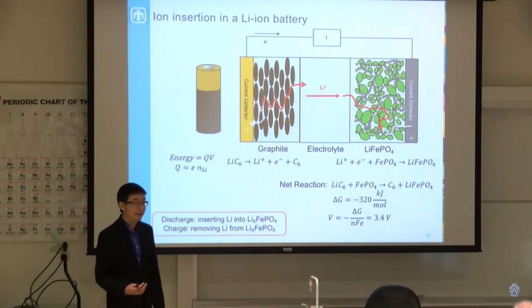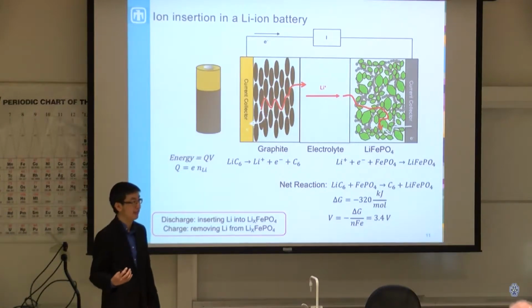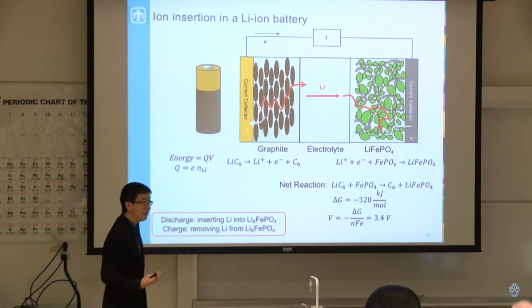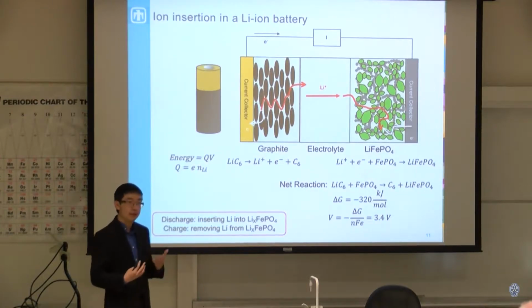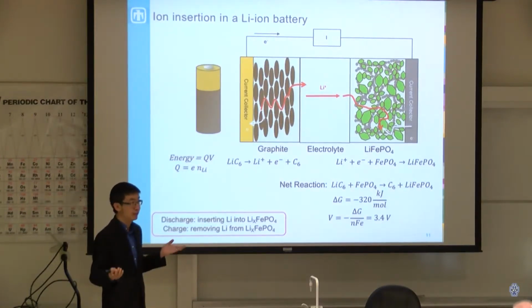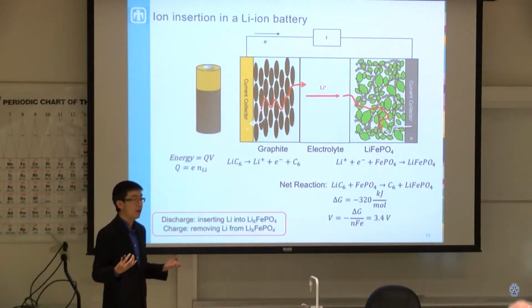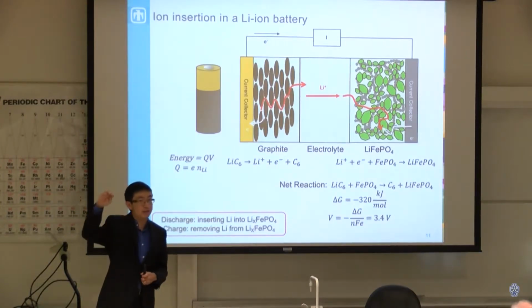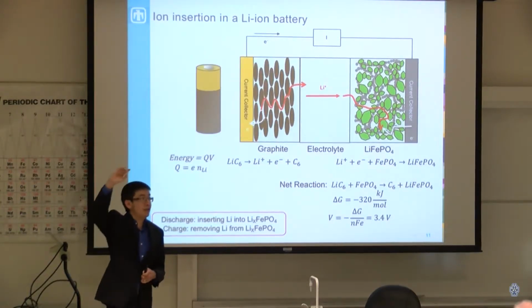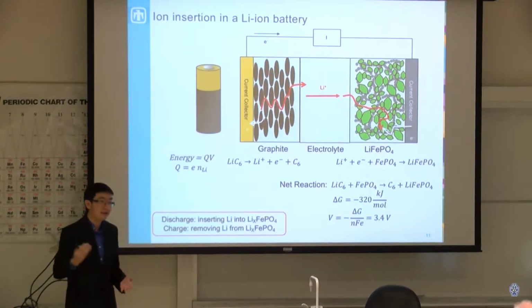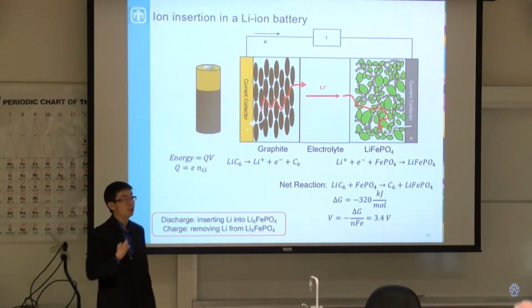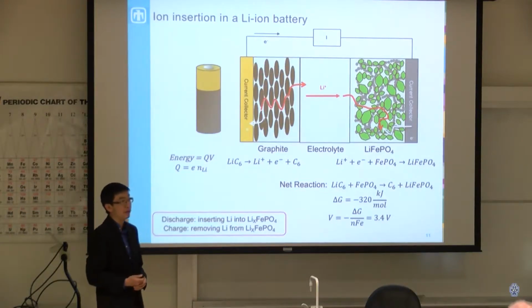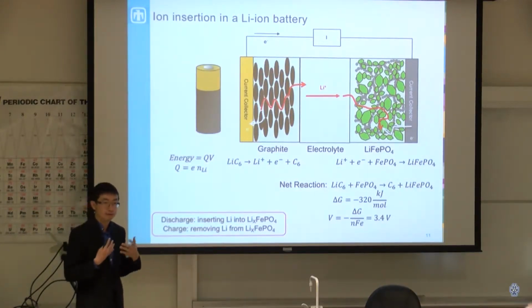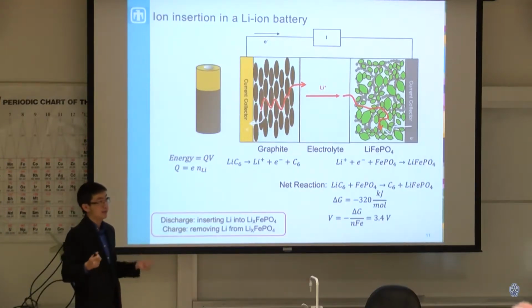I should follow up by saying that just because there's no electrostatic buildup, it doesn't necessarily mean the voltage stays exactly constant. Because in the end, it's about the free energy, and at the very least, you have an entropy component to the free energy, so that's going to change your voltage slightly. And if we go even deeper, one way to think about it is a semiconductor band model, whereby you initially fill the lower energy levels, so the more you charge, the higher the energy levels you need to fill. So the voltage of the battery does increase, but not nearly as much as you would think in a capacitor where you have an electrostatic buildup. So everything has to come through the physical bonding mechanisms, not through this electrostatics.